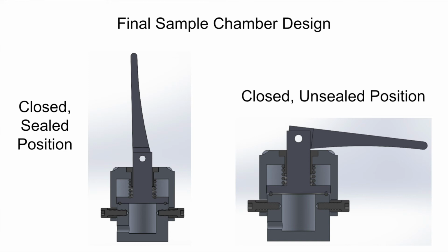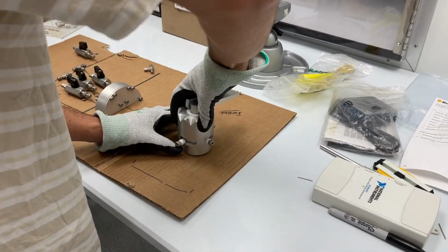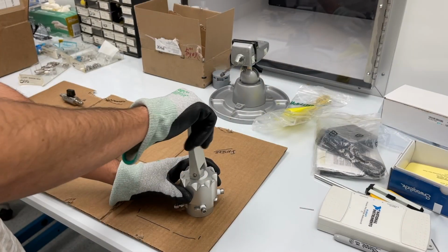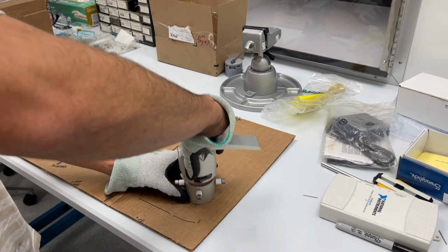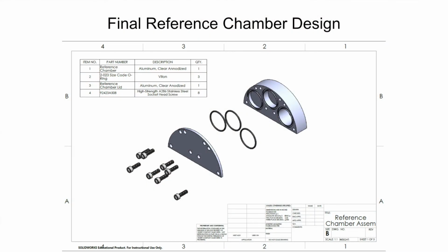It still used a spring-driven piston to seal the apparatus, but a cam lever was added to the piston for a number of reasons. With a cam lever, an adequately strong spring could be used in order to fully compress the O-ring. It also allows clearance for the O-ring while the lid is being installed, eliminating all shearing on the O-ring. The reference chamber is a much more simple design. Aside from cleaning and repairs, it does not need to be opened regularly, meaning screws and abraded particles were less of a concern as it will not be serviced in the glove box environment. The dimensions and numbers of the reference chambers were determined analytically as discussed above. The form of the reference chamber was to minimize the footprint of the assembly and to ensure it could be passed through the glove box porthole during assembly.